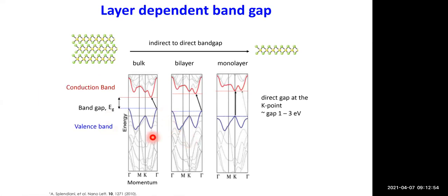Okay. So here, like I was talking about the indirect transition, which is basically in the bulk, you can see the lowest energy is an indirect one. That originates from the fact that the d and the p orbitals contribute to this valence band maxima over here. Now, if you look at the smallest direct band gap, which is this transition at the K valley, it is larger in energy than the indirect one, and these points originate from the d to d metal orbital transitions at these two points in the valence band maxima and the conduction band minima.